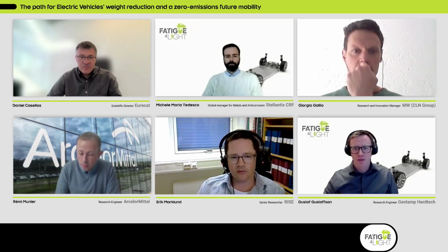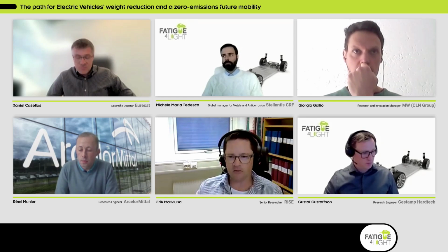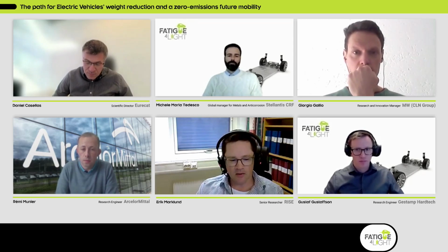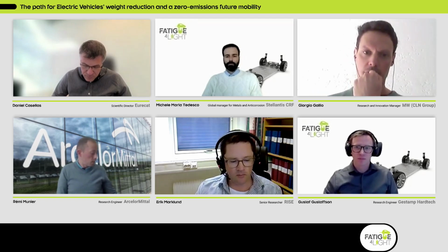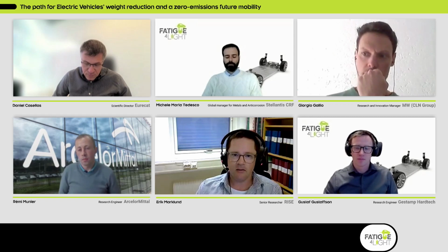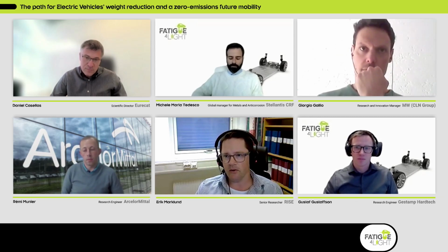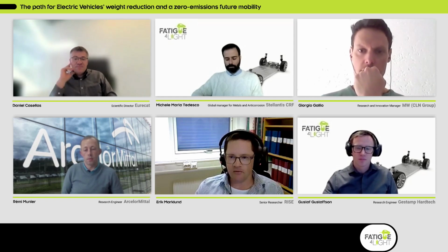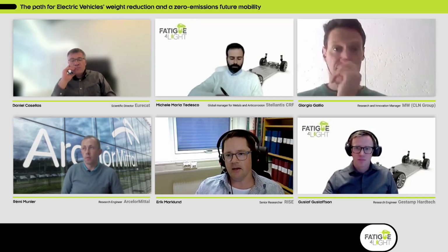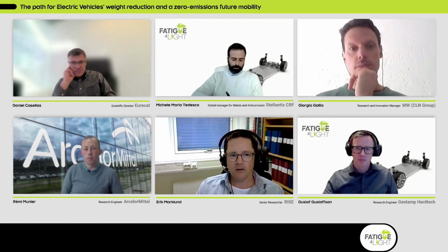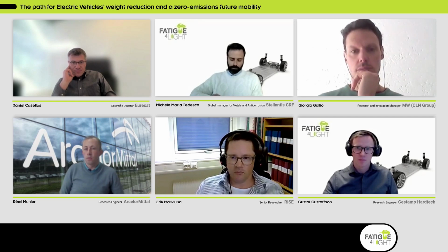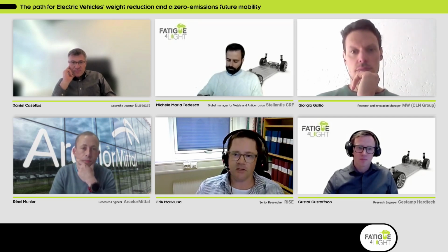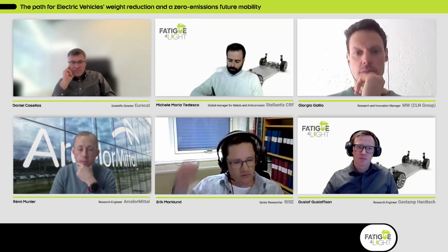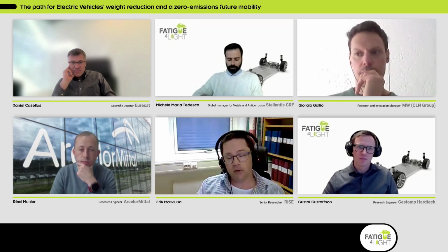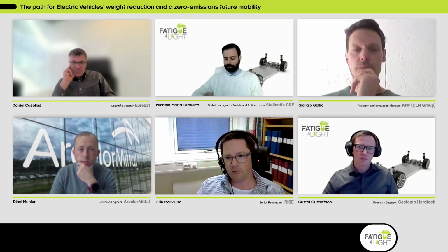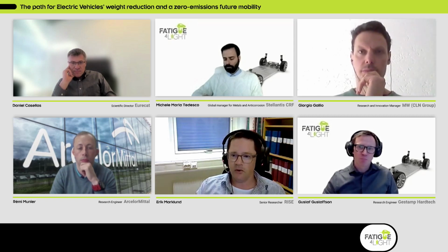So for composites, historically, fatigue wasn't really a big issue. I guess the reason was mainly because the ones doing simulations back then was mainly within aircraft, and they have no growth criteria. So they were testing and making sure everything was fine, but in terms of modeling in detail, it wasn't really as important, let's say. But then with the development of large wind turbine blades and then also automotive, fatigue became important again. Some of the challenges are, of course, that this material is anisotropic. So you have different response, different stiffness and strength in different orientations in the material.